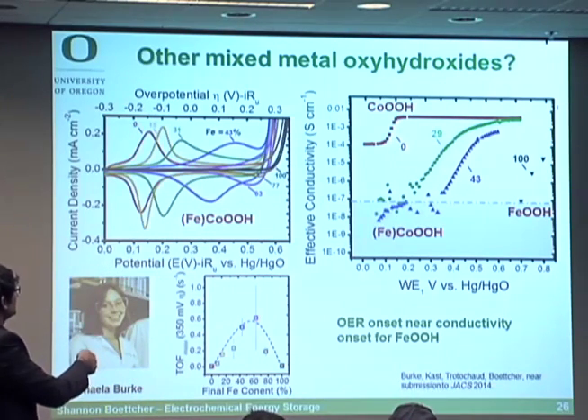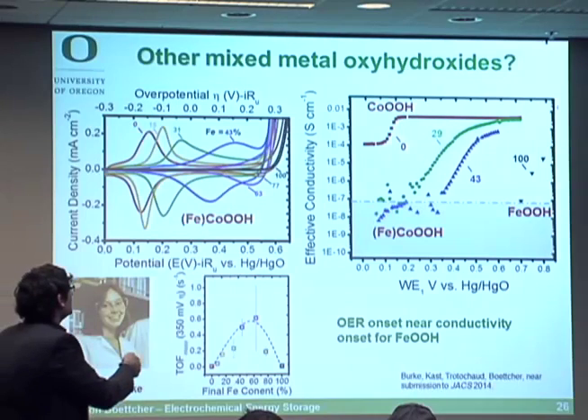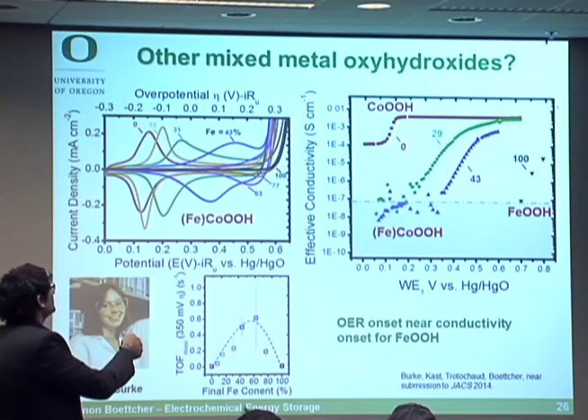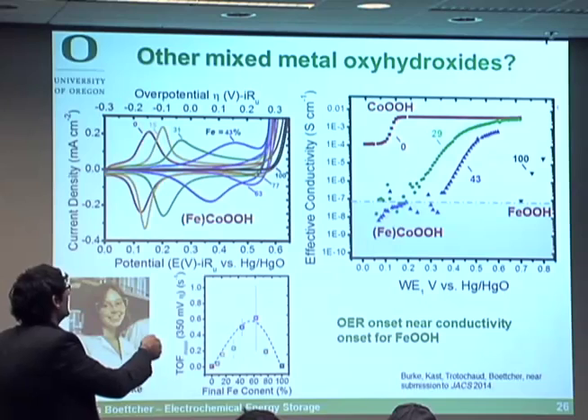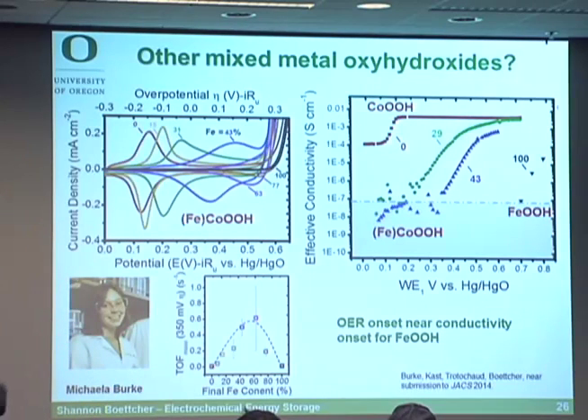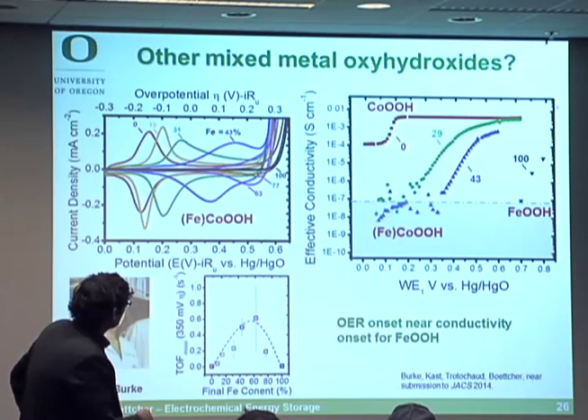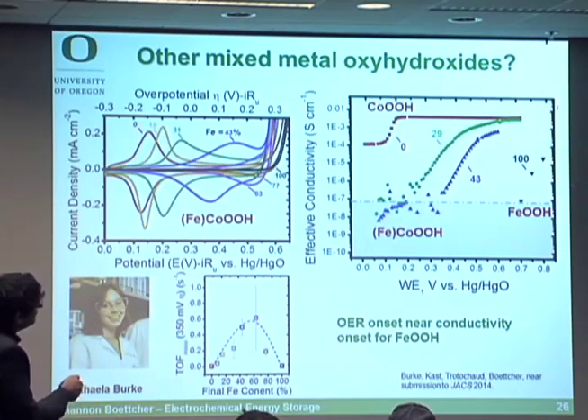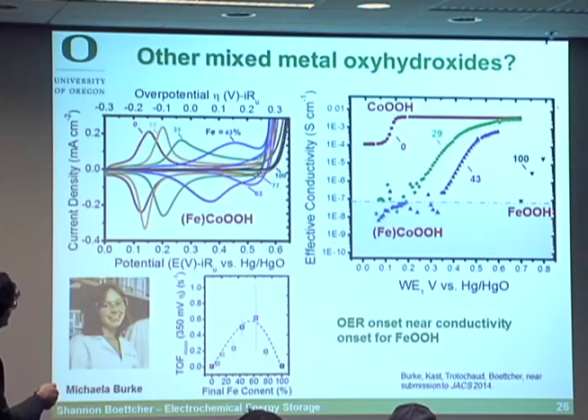The nickel hydroxides look similar. It's on a log scale now, so it looks a little different. But as soon as you oxidize the cobalt or nickel, the conductivity turns on, it becomes conductive, and then OER can happen out here once it's conductive. And conductivity is really important because you've got to deliver the electrons or remove the electrons. But if you look at iron by itself, rust, it's a really bad conductor.